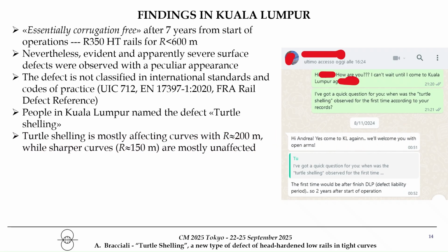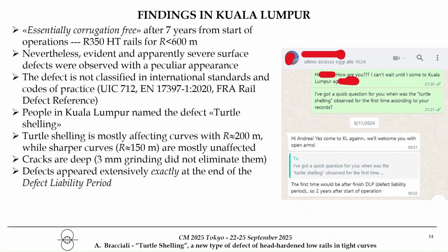So curiously, it is mostly affecting curves with 200 meters radius, but much less affecting curves with 150 meters radius. So sharper curve seems to be less affected by the problem. Cracks are deep, as I said before. And what's curious is that defects appear at the end of the defect liability period. So as any type of machinery that you buy, it breaks the day after the warranty is expired.